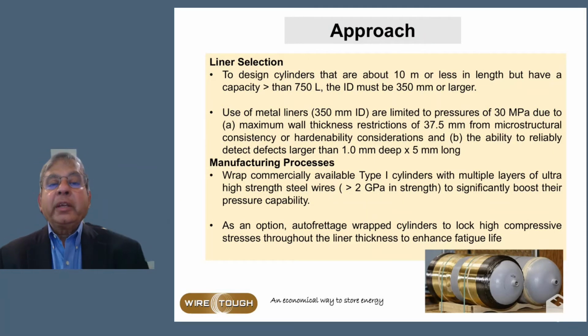Now, the approach that we have taken at WireTough is to basically use a liner that is reinforced with high strength wires. So in the liner selection, we design cylinders that are about 10 meters or less in length, but have a capacity of 750 liters, the ID must be at least 350 millimeters or larger. Use of metal liners of 350 millimeter ID is limited to pressures of 30 MPa due to, A, maximum wall thickness restrictions of 37.5 millimeters from microstructural consistency or hardenability considerations, and B, the ability to reliably detect defects larger than 1 millimeter deep and about 5 millimeters long on the surface.